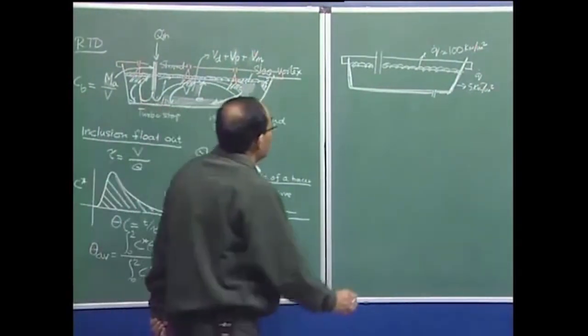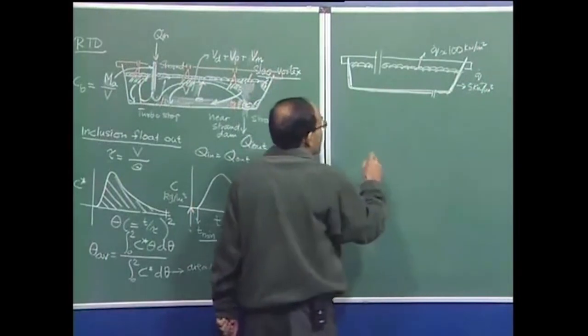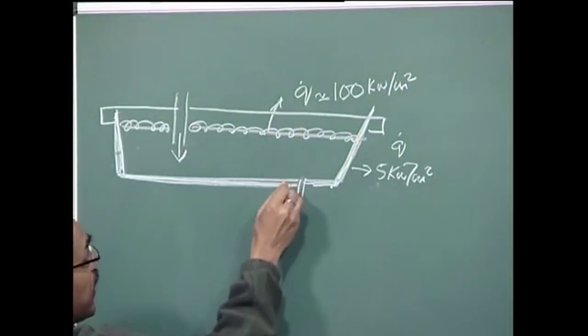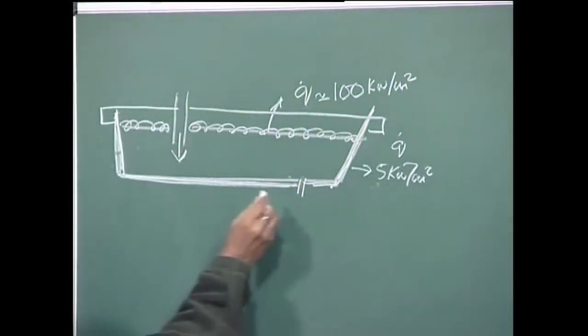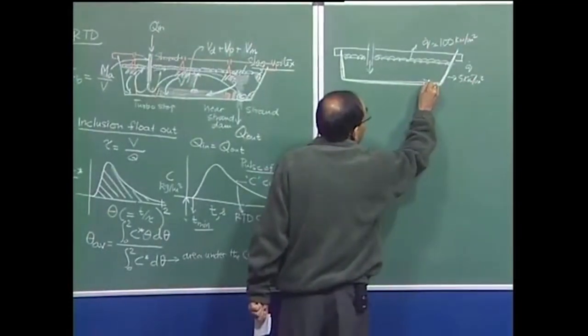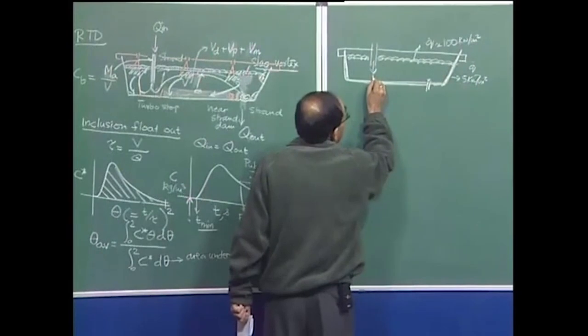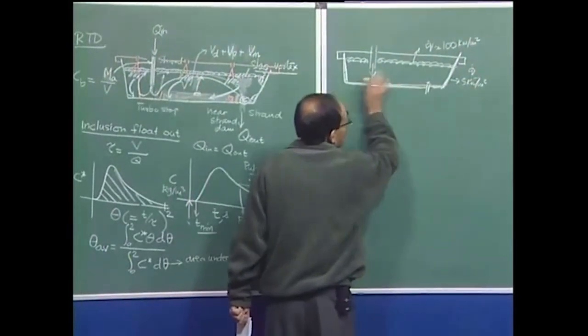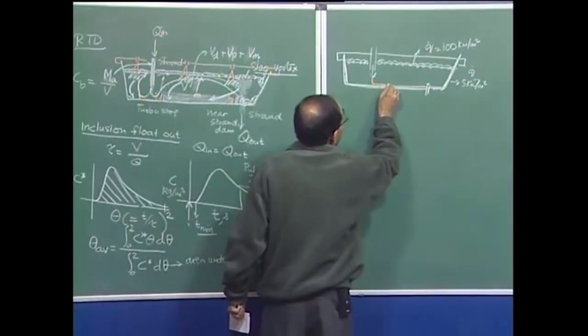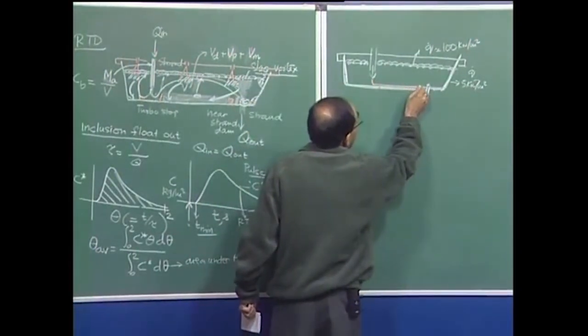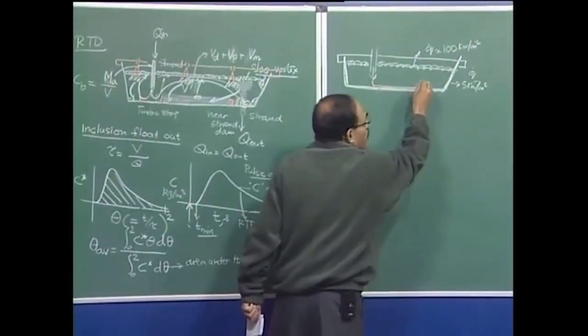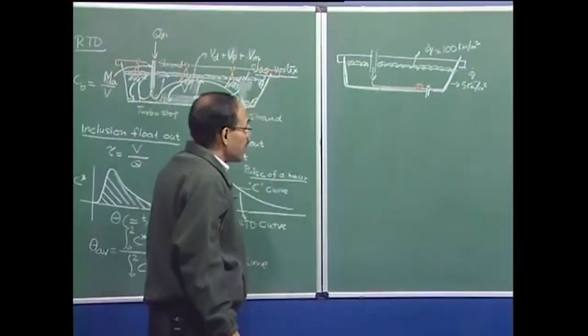If people pour molten metal at a high temperature to compensate for heat loss and prevent premature freezing, we may land up with material in the mold at a higher temperature than desirable. So material entering the mold may have a larger temperature. The inlet mold temperature is actually more than desirable, and as mentioned, the higher the temperature, the lower the casting speed must be, because you have to keep the molten metal in the mold for sufficient time to build a reasonable shell thickness — otherwise there will be breakouts due to higher hydrostatic pressure.